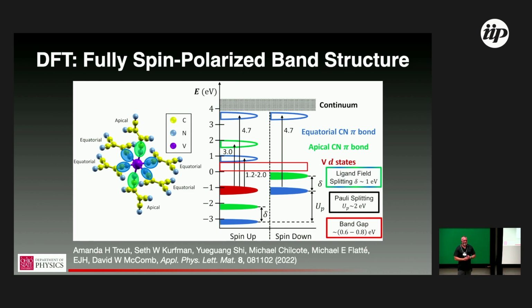So I think what you're pointing to is the challenge that you often have with the band gaps, particularly of semiconductors. There are a few wrinkles here. One is that the main issue with typical semiconductors is that their mass is very light, and that means that small errors can balloon in terms of the band gap. The mass here is quite heavy, so it's much less susceptible to it. You can do the standard things. You can do the calculations with and without U. You can do hybrid calculations with the standard mixing parameters, and they all take you towards this 0.7 eV band gap, which is relatively robust.